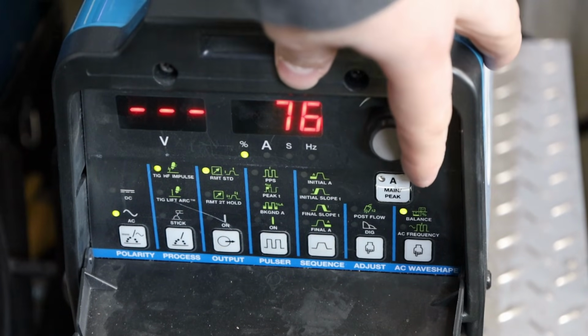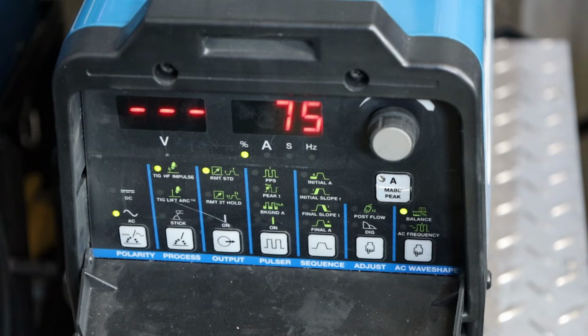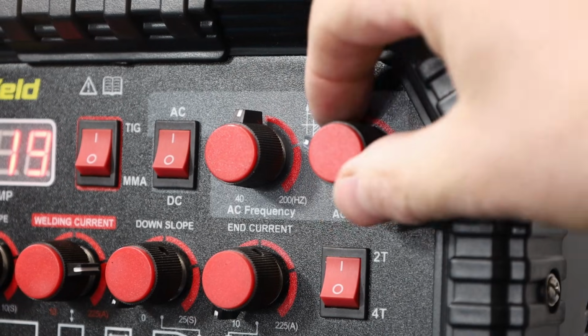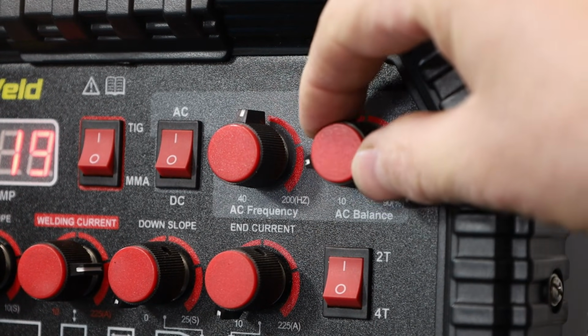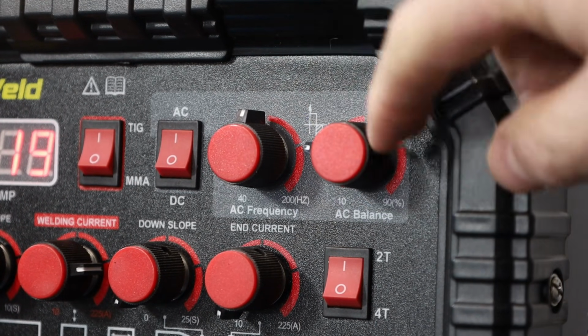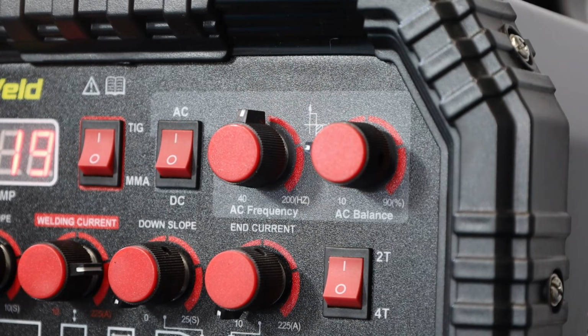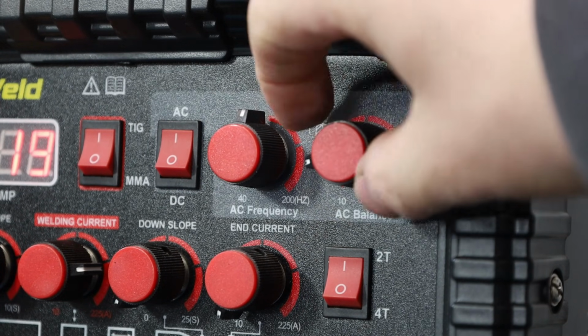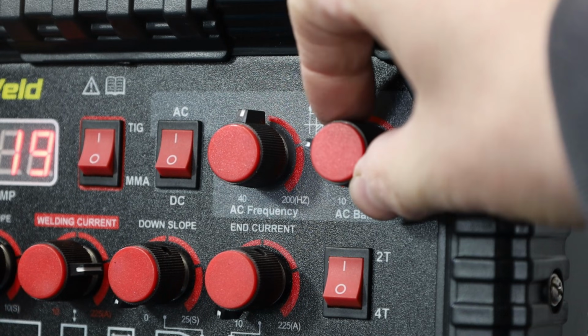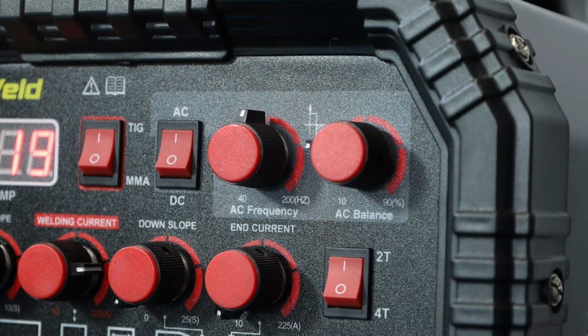So on my Miller Dynasty here, I set the number at 70 or 75 on AC balance, and that 70 or 75% of the time is negative. On my Prime Weld, on the other hand, I'm actually setting how much of the time is positive. So I need to turn it clear down to 25 or 30% to get the same result that I get at 70 or 75% on my Dynasty.